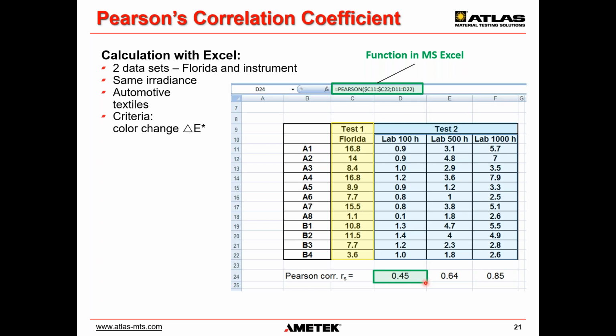Some tendency maybe, but not a good correlation. But you can do the same calculation after 500 hours. It gets a little bit better. And you can do the same calculation after 1,000 hours in the instrument. And it's actually 0.85. I would consider that a good correlation for 12 materials. So there is correlation between 1 year Florida and lab weathering after 1,000 hours.